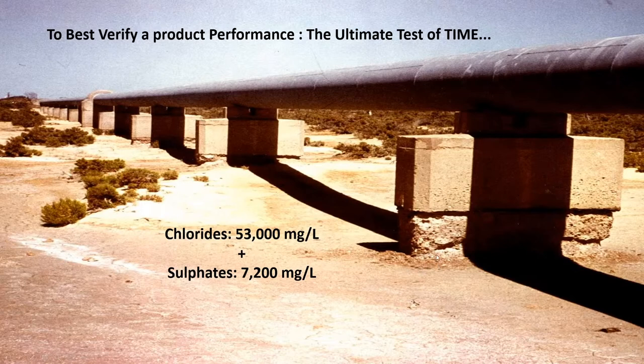What you can see at the bottom here is massive sulfate attack. You've got sulfates of 7,200 milligrams per litre in the soil, and chlorides at 53,000 milligrams per litre, which has caused an awful lot of salt scaling. So this is what they look like after 2 years. We were asked to come up with a proposal to try and repair them rather than knock them down and rebuild them. It's a water pipeline running across the desert serving a few local communities.